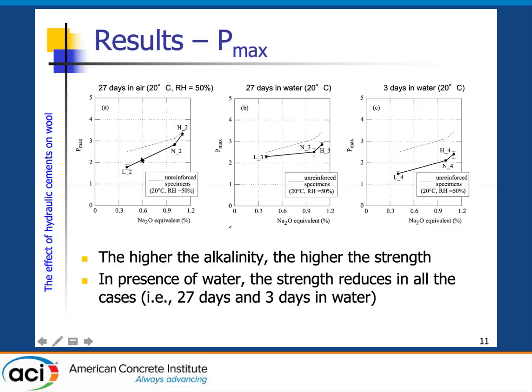If you introduce these specimens in water, you have more or less a reduction of the strength, and you cannot see a great difference between the different types of cement with respect to the maximum load, as you can see in the previous one. This is the case in which the specimens were stored 27 days in water. If only 3 days in water, of course you have more or less the same behavior, but the strength is lower because we have a kind of early stage strength of concrete. But this is only the effect on the strength.